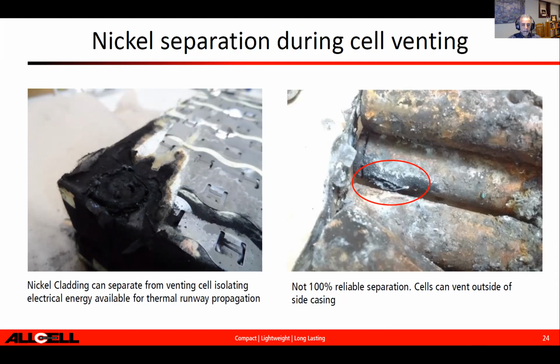However, we found that there's significant issues with the casing, even into metal casing, that there's something that's called side rupture. And the side rupture, basically the electrolyte exit that, and it's like a torch that actually goes directly to the adjacent cells and causes major problems. And those are things that we have to design for. But the one with the current dumping is something that we investigated further.